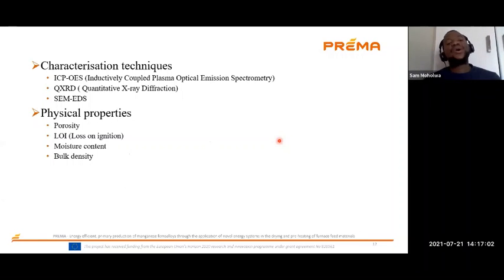The as-received ore was taken for the following characterization techniques. We have ICP-OES to determine the chemical composition, we have the quantitative XRD to determine the minerals present and their quantity. Then we took them for SEM-EDS to determine the texture and other properties. Then after preheating this ore, the sample was taken through the same characterization techniques.